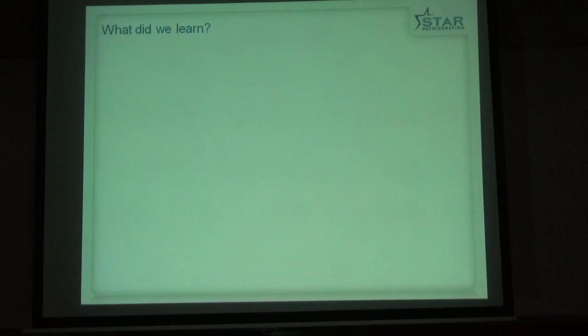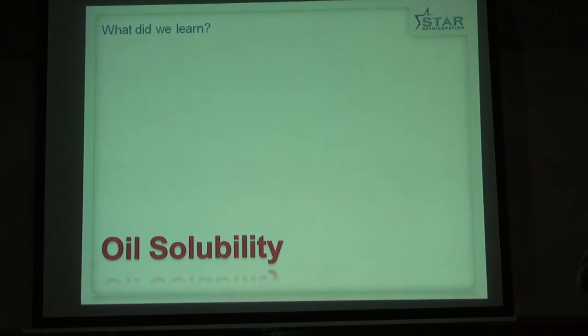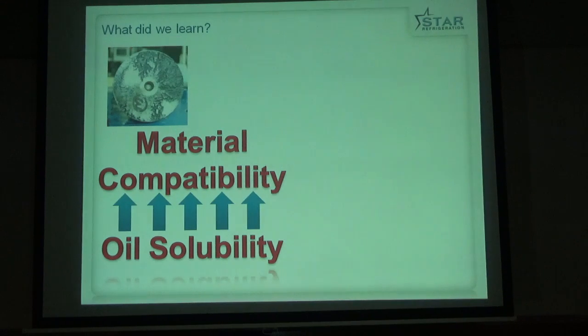So what did we learn from doing these systems? There was a challenge with oil solubility. Everybody knows that ammonia is insoluble in oil, except that when you go to these high temperatures and pressures, we find solubility about 4%. This is an aluminium balance piston from inside one of the screw compressors. And what's actually been happening here is that the ammonia has been absorbed in the oil and there's been a vibration between two very close surfaces which has caused cavitation on the surface of the aluminium. It's knocked the protective oxide layer off and we've got this heavy corrosion underneath because of this oil solubility problem. So we've had to look at alternative materials for some of the components in the compressor.